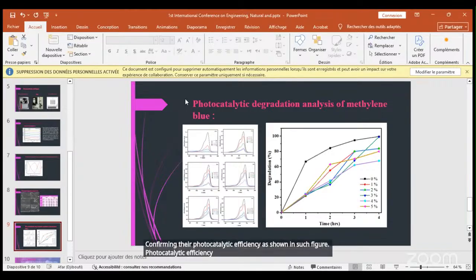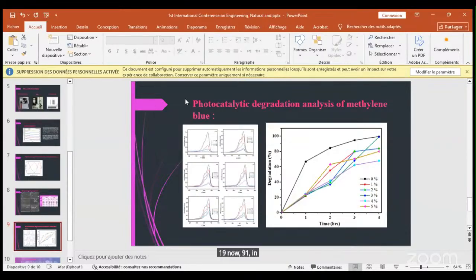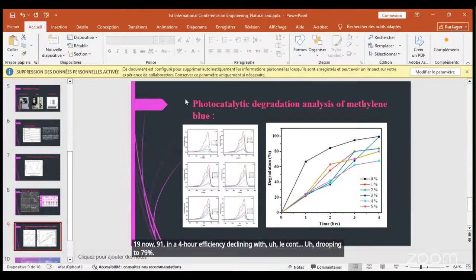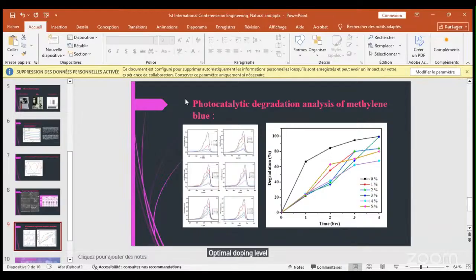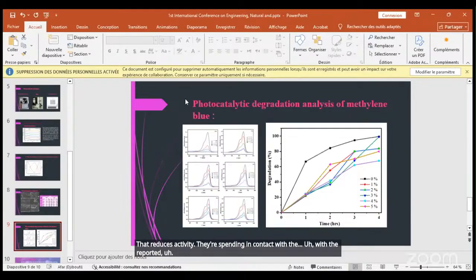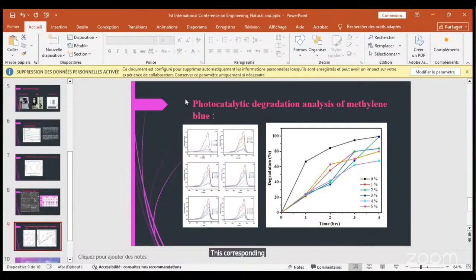Photocatalytic efficiency varies with aluminum doping. Undoped zinc oxide achieved the highest degradation, 91% in 4 hours, with efficiency declining as doping increased, dropping to 79%. At the optimal doping level, aluminum introduction created defects and recombination centers that reduce activity. This finding contrasts with the reported results, with a corresponding possibility due to the different synthesis or the testing conditions.